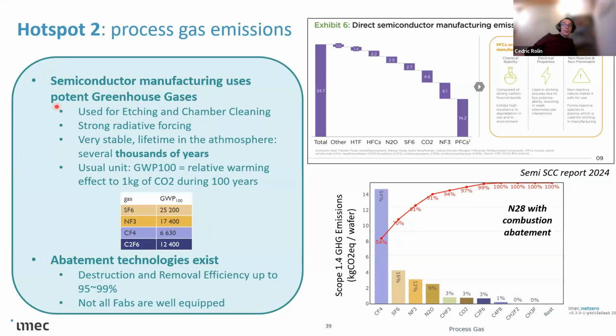So yeah, the industry uses potent greenhouse gases. They have a strong radiative forcing, so it means that they will actually absorb a lot of the infrared emissions from the planet, and they have a very long lifetime. So in total, they have a high GWP, and here it is showing actually for four different gases used by the industry, the very high value of GWP. SF6 being actually the worst case, where you release 1 kilogram of SF6, it is equivalent to 25 tons of CO2 equivalent.